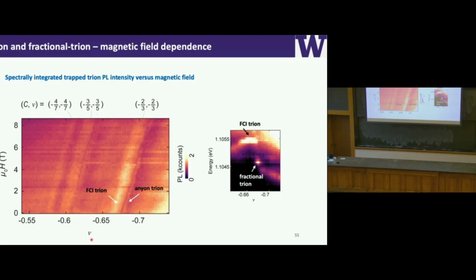Okay. So all this shows that this new feature I show you, this narrow trion state, which only appears at the doped FCI and which I call the fractional trion, has these 2/3 topological features. The reason this is important is that this anyon-trion is actually bound to a fractional charge, and this fractional charge only exists in the system in this 2/3 FCI state. So now I show you this evidence, right, that when we dope this FCI state with mobile trions, a new state appears at the lower energies. This is very close to the example I showed you in the 2D electron gas system, right? And that shows evidence of this fractional charge trion state.